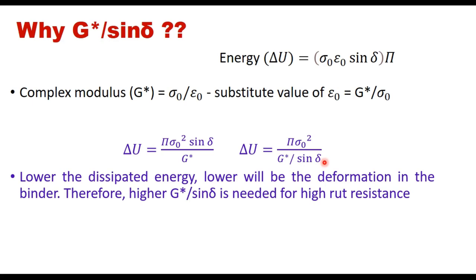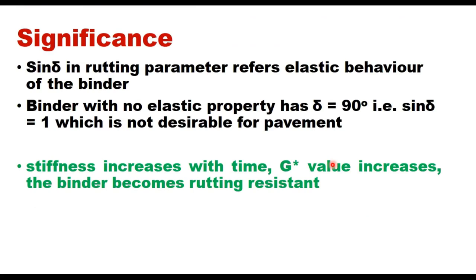Lower the dissipated energy, lower will be the deformation in the binder. Therefore, G*/sin(δ) should be higher. You can say that high value of G*/sin(δ) is required for high resistance.